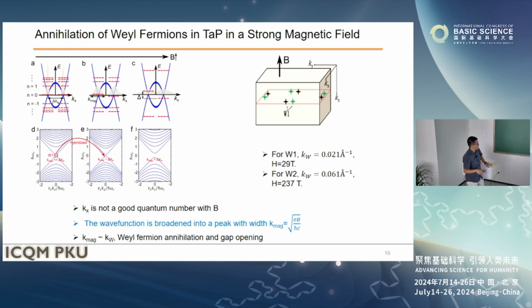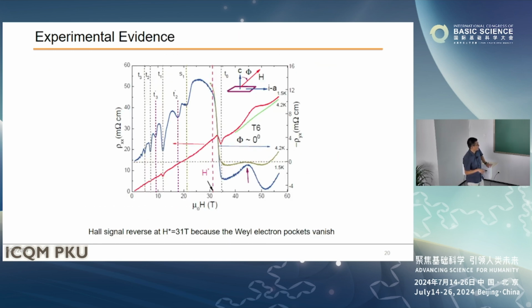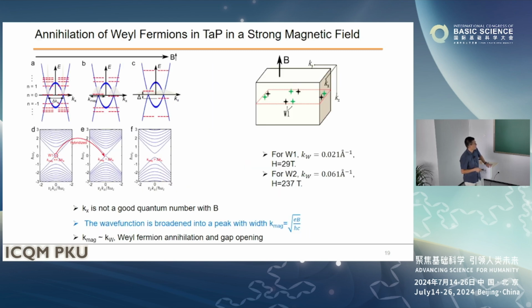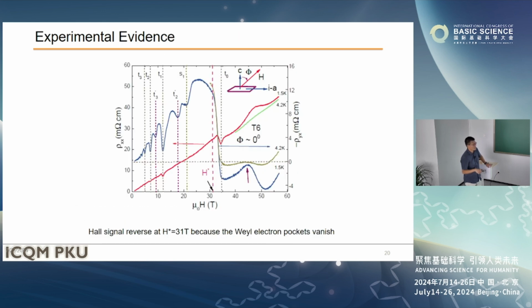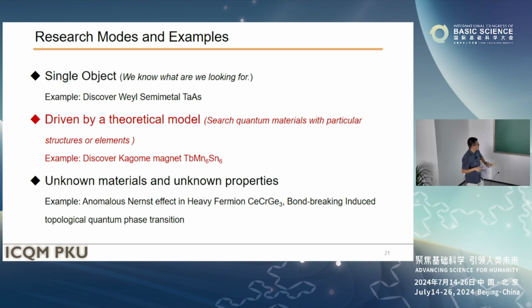And indeed, we observe this situation at a field of around 35 tesla, 31 or 35 tesla. Here we show the Hall resistance response. You see at around 31 tesla, it has a sign reversal because the Weyl one, this one, is an electron pocket. When it's annihilated and opens a gap, the only thing left is some hole pockets. So that gives you a sign reversal for the Hall resistance. Okay, so these are two works we did 7 or 8 years ago.